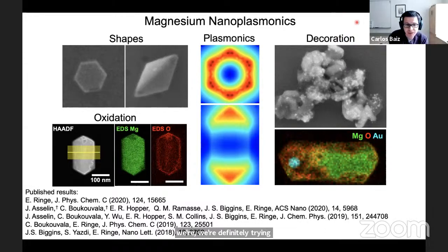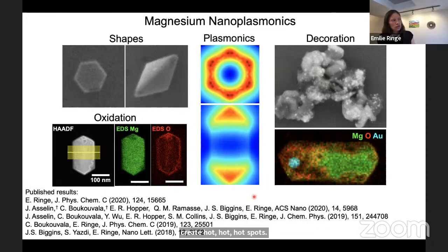And the last question from the audience is the following: given the multipolar resonances that you get with the shapes, what do you gain or lose by fabricating coupled nanostructures to create coupled modes and create hotspots? Yeah, in these structures, you can actually get a hotspot of much higher electric field by coupling two nanoparticles rather than relying on the intrinsic higher order modes in these structures. That also would enable you to maneuver the plasmon resonance so that that coupled plasmon is likely to be at higher wavelengths, a lower energy than an uncoupled mode. I think there would be something to gain in there.